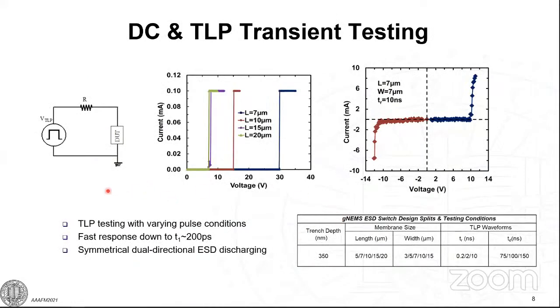So we start to do the characterization using the very fast transmission line pulse testing, which is the square wave. The square wave has duration TD and the rising time TR. We first did a lot of structures with different dimensions: the membrane length and the width, and the trench depth over there.